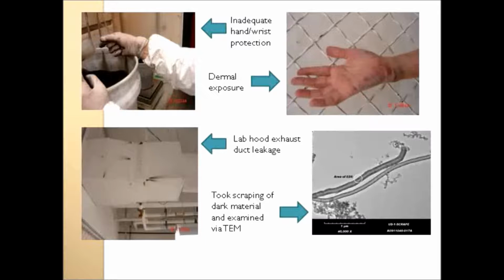Again, here's somebody involved in wet cutting with a circular saw, nanomaterial composite. So here we have the carbon nanofibers embedded in a plastic composite material. And as Paul mentioned earlier, the thought was, well, once it's bound into a matrix, it's an epoxy, these fibers will not be released. Well, this slide tends to say otherwise. This material here does end up in his breathing zone, potentially, if he was not protected. He's wearing a mask. And you can see that the material is fibrous in structure. We did confirm it with TEM and EDS.